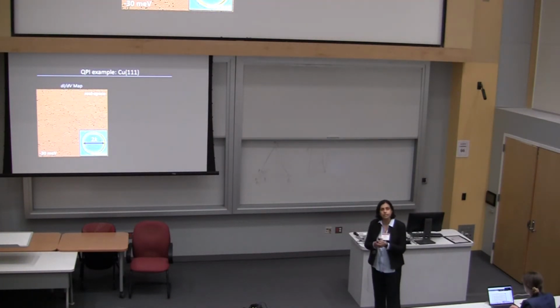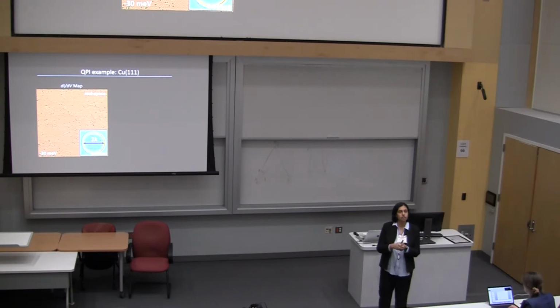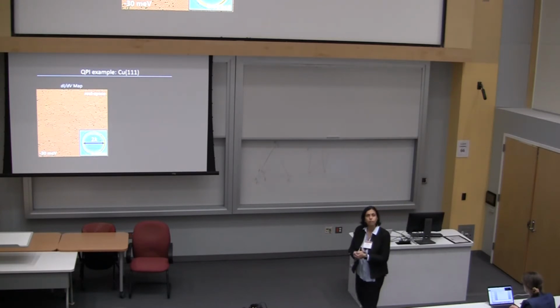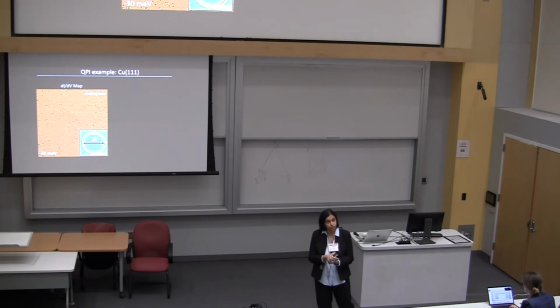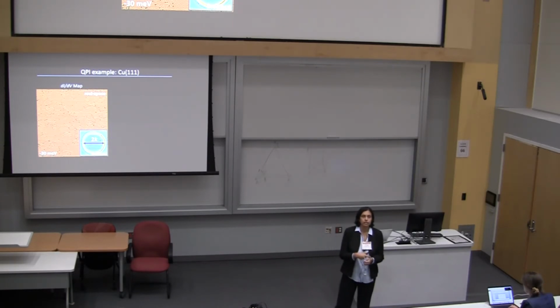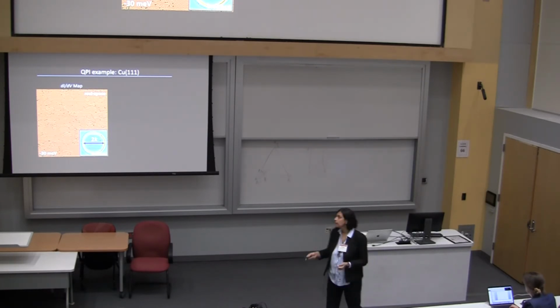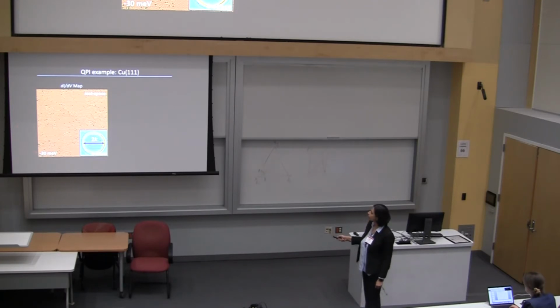Copper has a surface state which has a parabolic dispersion. The electrons on the surface of copper literally behave like free electrons, except with some kind of renormalized mass. Okay, so here you see a dI/dV map, and you have many scattering centers. And here's what it should look like in momentum space.